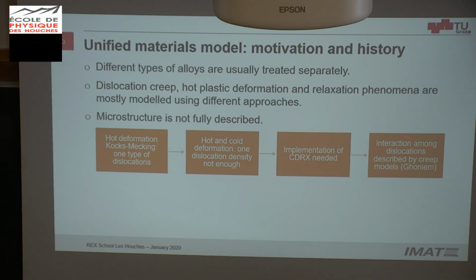Then we replaced the H and R, so hardening and recovery, by the Gourdet-Montheillet equations. These equations come from creep, not from hot deformation. They are very old equations that describe what happens during dynamic recovery in dislocation creep, not diffusion creep. What happens with the interaction of dislocations? There are rate equations that express that if I am a mobile dislocation and I get stuck somewhere, I become immobile and increase the wall dislocation density, transforming into another type. So it's a reaction type equation.